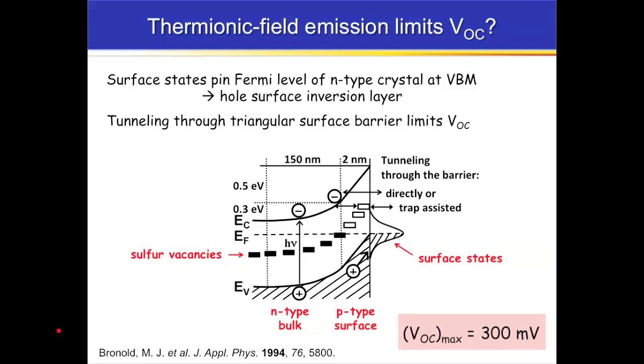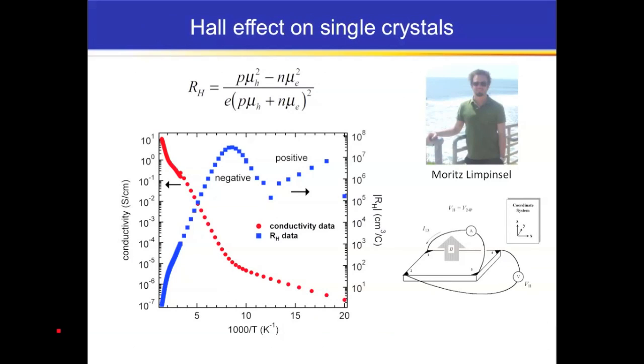surface. And so what we're doing in order to explore all of these ideas and find out what's wrong with the voltage is Hall effect measurements on single crystals. And then we're going to link this back to thin film data. What you get out of a Hall effect measurement, the raw data, is conductivity and the Hall coefficient, or the Hall voltage. And I'll talk about the conductivity in a second. It looks fairly normal. We've got 3 different activation energies approximately.